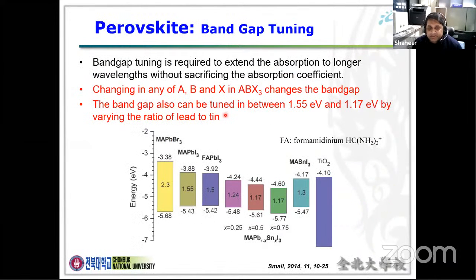And another interesting thing in perovskite materials is that they have a tunable band gap. It means that if we change the A, B, and X, it can change the band gap. Like you can see in this picture, if we change this MA to FA, you can see the HOMO and LUMO values of the perovskite are changed. Similarly, if we change the lead to Sn, it can also change the band gap. This is also one of the important characteristics of perovskites. That's why it is highly flexible. According to our need, we can tune their band gap.